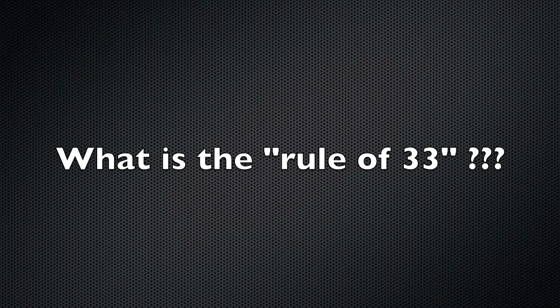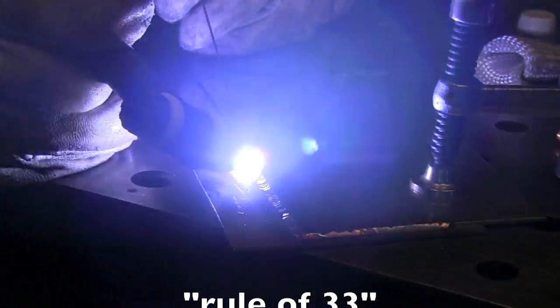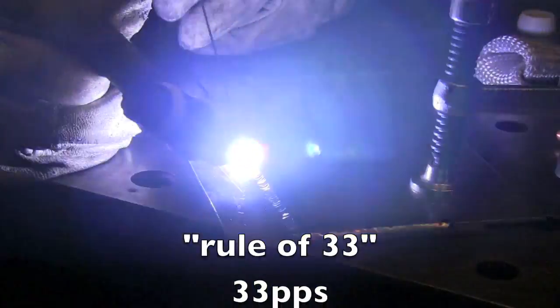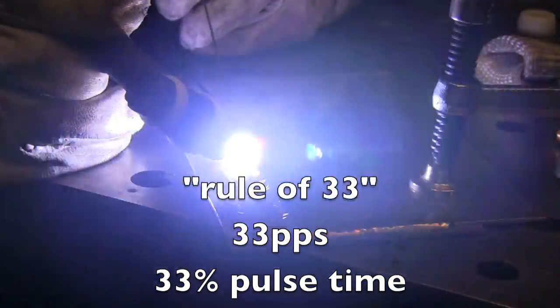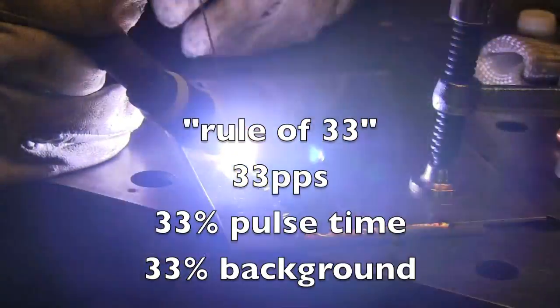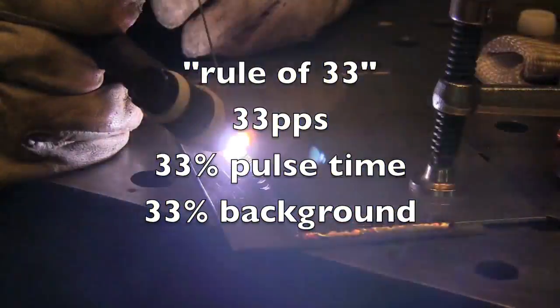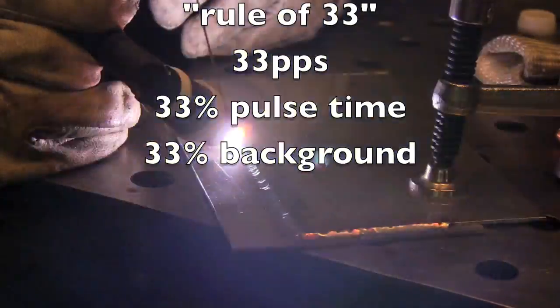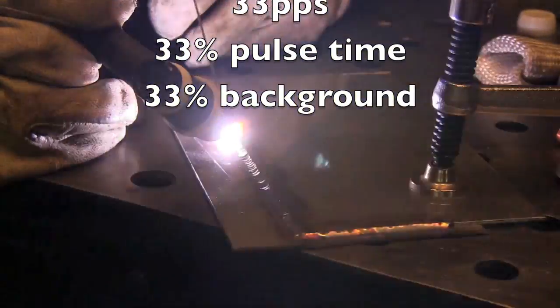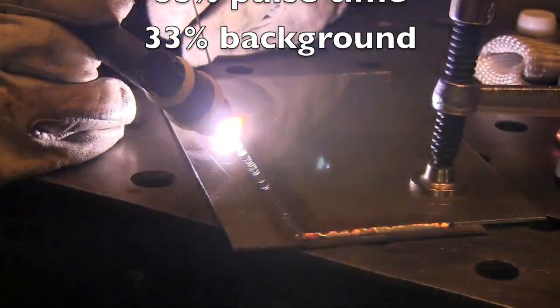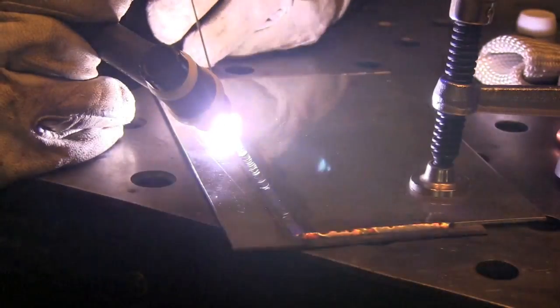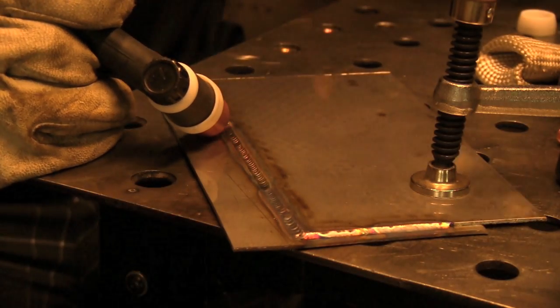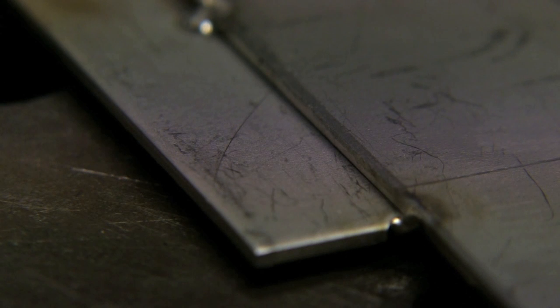Now, what is the rule of 33? I've been talking about that in a lot of videos. It's basically, if you have an inverter that's got pulse capability on it, 33 pulses a second with 33% on time for the pulse and 33% background is a really good starting place, and it works exceptionally well on thin stainless like this in keeping the heat down and moving that puddle along with a minimal amperage. But you got to have an inverter. Most transformers, none of them that I know of, are capable of 33 pulses a second, and I don't want to watch anything that's slower than that.